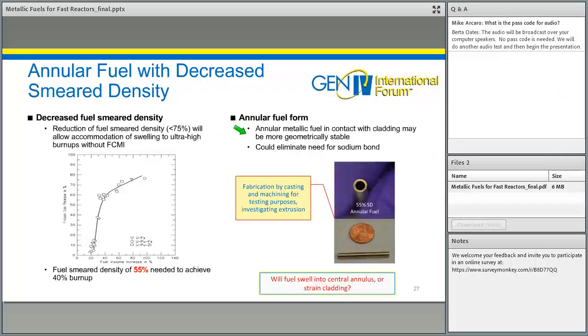There are some questions on how geometrically stable that will be under irradiation. It may be subject to some strange effects. Some people are concerned about slumping that you certainly wouldn't want to happen. And so to address that issue, we've been looking at annular fuel, which may be a better geometrical form for these low smear density fuels. So what you're looking at here is not a piece of cladding. This is annular metallic fuel slug, 55% smear density. That would be put right into a cladding tube with essentially contact with the cladding right from fabrication.